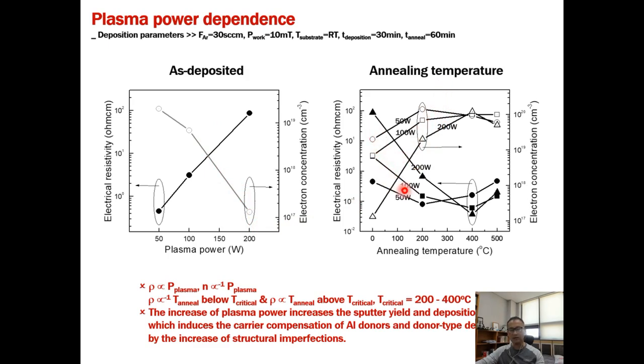In the right figure, electrical resistivity decreases with the increase of annealing temperature until 400 degrees centigrade. Above 400 degrees centigrade, it has a tendency to increase. The electron concentration is vice versa. We can say that the increase of plasma power increases the sputter yield and deposition rate, which induces the carrier compensation of aluminum donors and donor-type defect by the increase of structural imperfections.